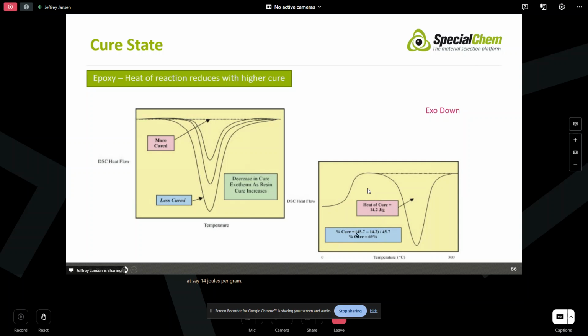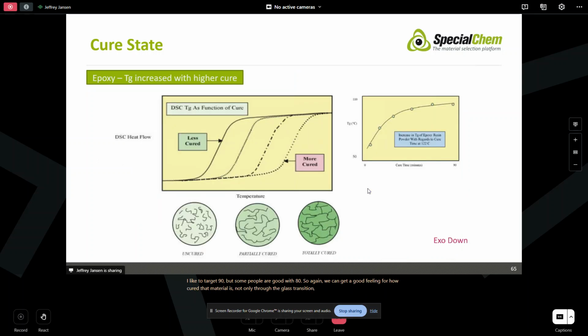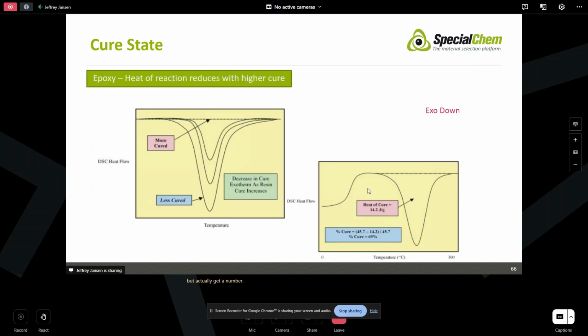Actually, this is for our sample. We know that our raw resin has a heat of fusion of 46. We subtract that, we do the math, and we can come up with our cure percentage. Now, typically, you're looking for a cure percentage in thermosets of 90% or above, or 80% or above. I like to target 90, but some people are good with 80. So again, we can get a good feeling for how cured that material is, not only through the glass transition, but actually get a number by looking at the residual cure that's left.